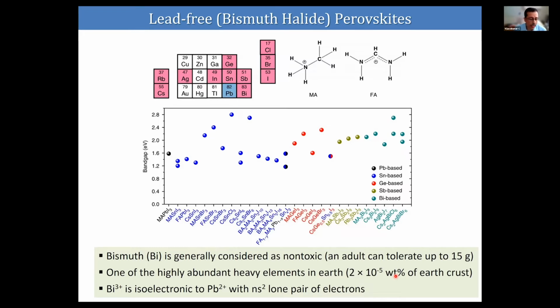And most importantly, this Bi3+ is isoelectronic with Pb2+. You can see the atomic number of lead is 82 and bismuth is 83. So bismuth 3+ is isoelectronic with lead 2+, and it has a similar ns2 lone pair of electrons, just like lead. The presence of the ns2 electrons was found to be the major reason for most of the optoelectronic properties of lead. So that is why we selected bismuth as a possible choice for replacing lead, and we decided to study bismuth halide perovskites and see what the possibilities are.